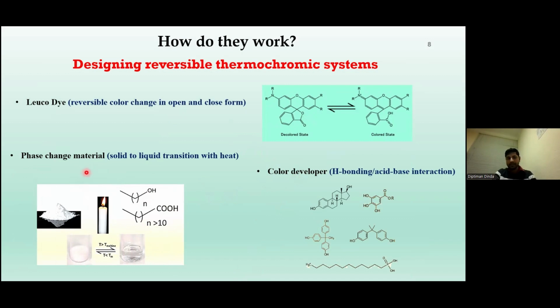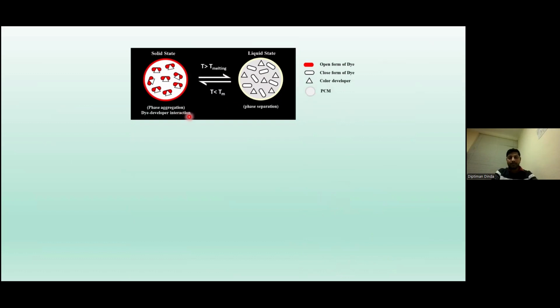Actually, this phase change material, which basically is an aliphatic acid or alcohol, will change its phase from solid to liquid when we apply heat, and because of the phase change, it will release energy, and that energy will be used to stabilize the open form of the leuco dyes in addition to the color developer. So if we look at their mechanism, in the solid state, as the color developer and the dye are phase separated from the PCMs, they will try to agglomerate, and they will interact with each other to stabilize the open form of the leuco dyes, forming the color in the solid state.